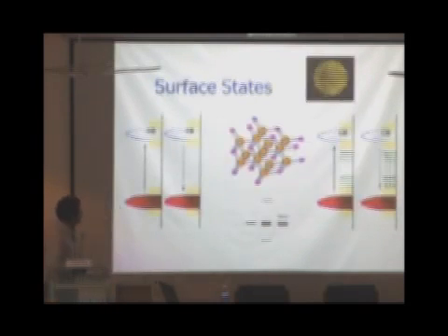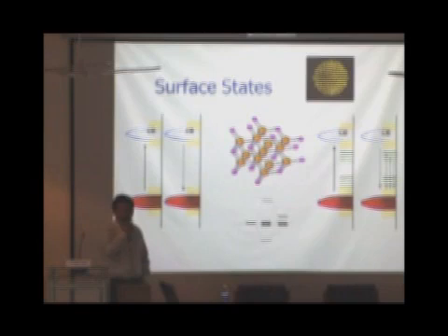Surface state emission. Now the thing is that you have a lot of surface states on nanoparticles, and you can think of them, for example, as a tetrahedral bond. An atom inside in the bulk has all 4 bonds or 4 valencies satisfied, but an atom on the surface would have either 1, 2 or 3 bonds pointing outwards.